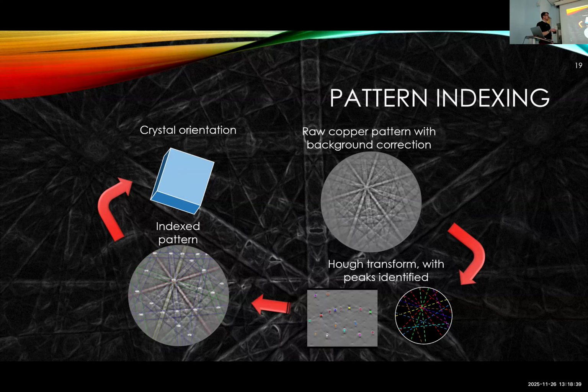To work out which crystal plane is which, some clever people in about the 1990s realized that you can use, there are two similar mathematical formulations, the Hough or Radon transform, that effectively transforms a straight line into a peak, and the peak now contains a bright center and dark edges. And if you find that peak, computers like finding single peaks rather than diffuse bands. That's just the simple bit of how searching spaces work for that.